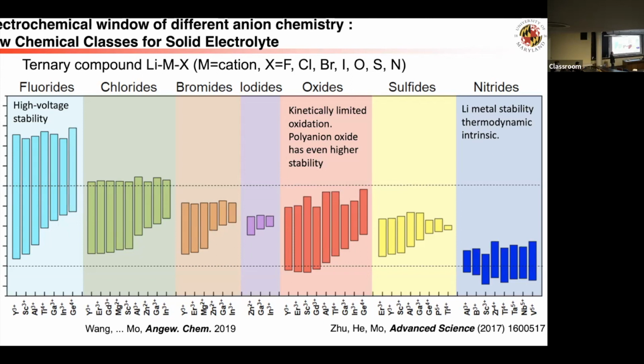If it's pure, you can do this significantly. Sometimes you do reach a limit because too much lithium is not good, so then you have to look at the detailed diffusion mechanism. There's a certain range you can dope across a whole composition range, but you have an optimum somewhere, and if you go over it, conductivity starts dropping. That's really up to the specific diffusion mechanism. Yeah.